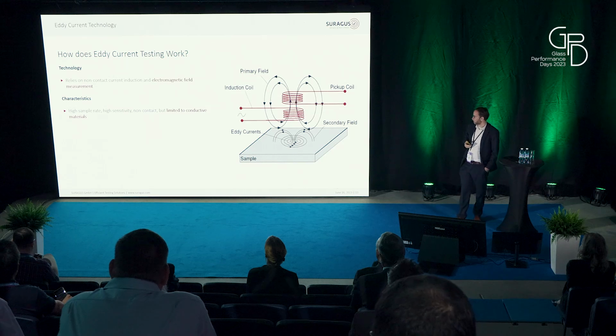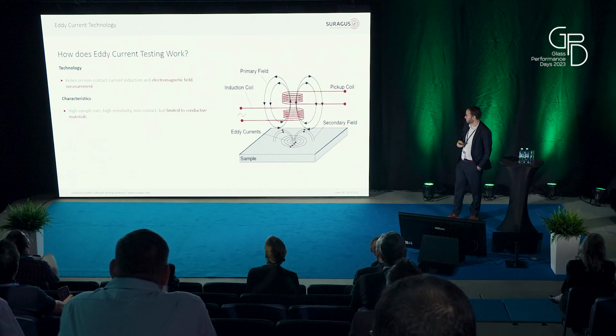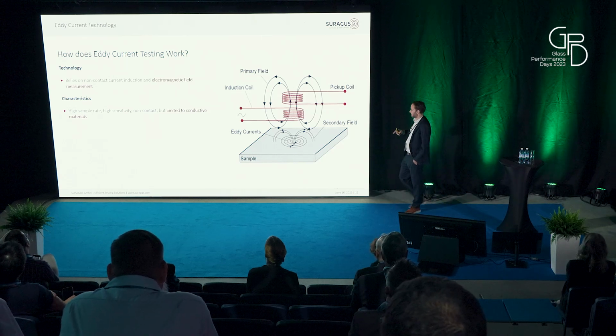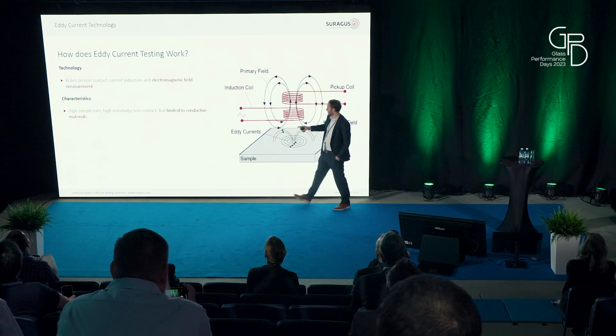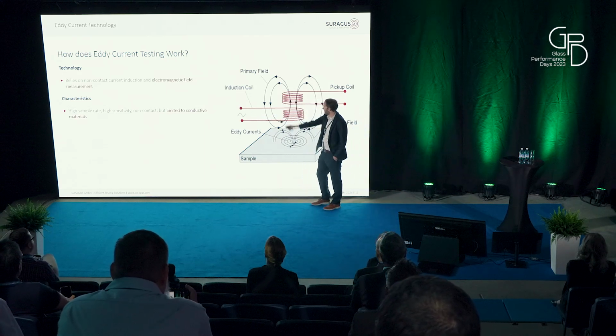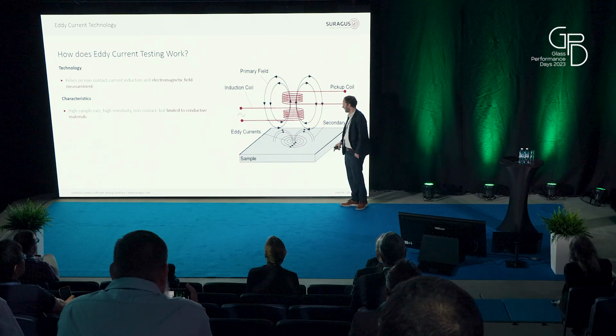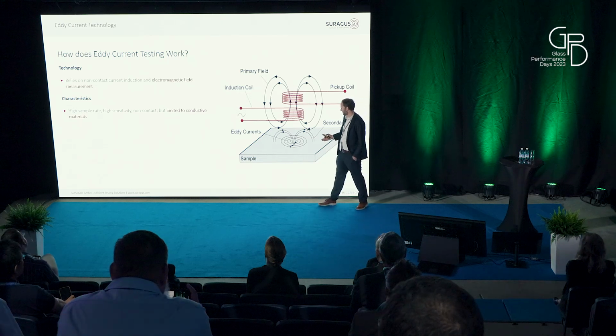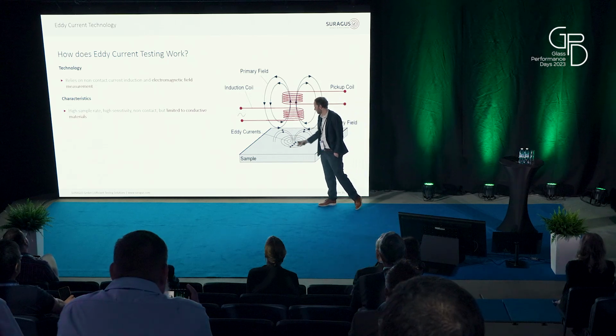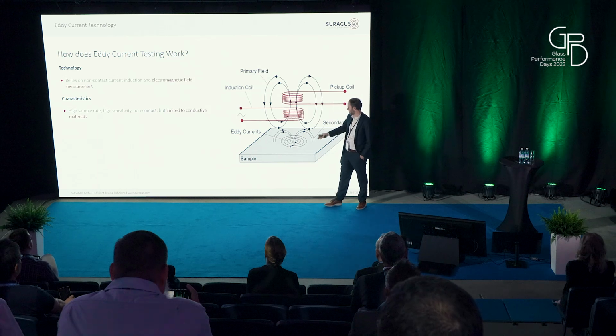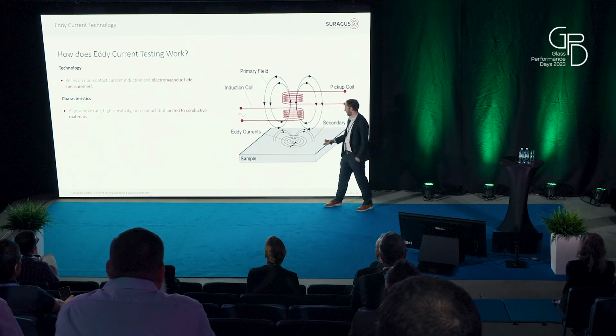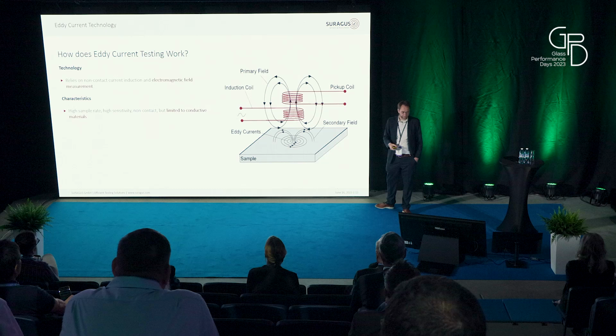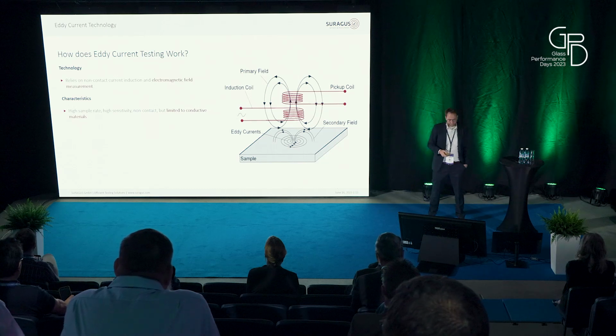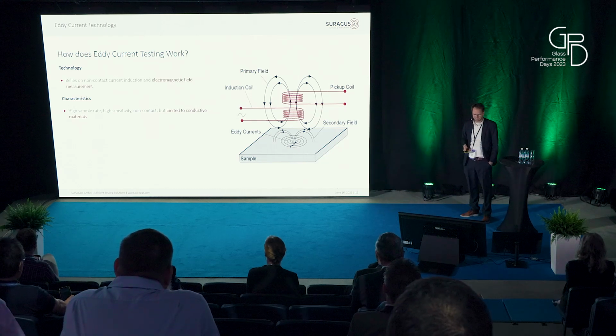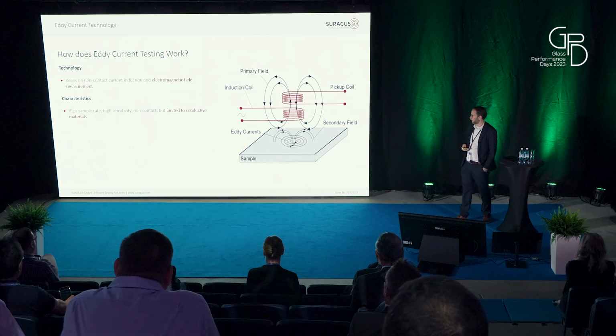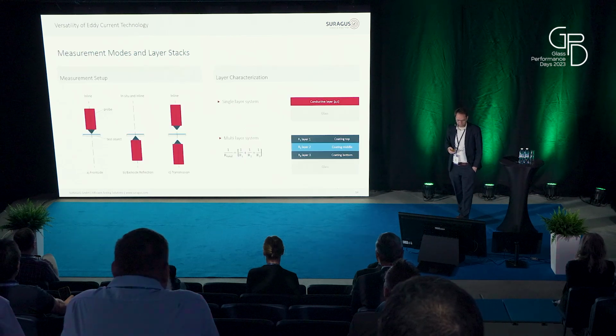Eddy current is known by many people, but I'll give you a very brief summary. Basically, what is happening, we apply an alternating current to a coil. This is generating a primary electromagnetic field. And if you bring a silver coating into this field, eddy currents are created. This changing current is generating a secondary field, and this secondary field is then picked up by the sensor and is characterizing the field and then correlated to sheet resistance or emissivity.